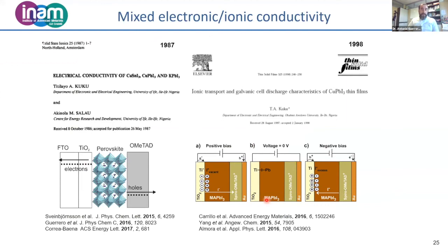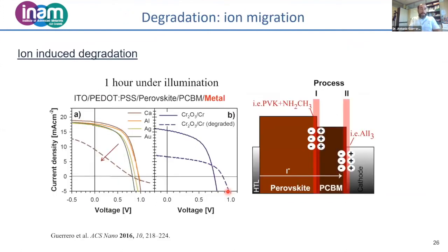Well, perovskite solar cells, as you know, are mixed electronic and ionic conductors. This has been known for a long time, from 1987 and 1998. There are some papers on the mixed electronic and ionic conductivity of perovskites. And then once we had the perovskites, MAPI and all this family for solar cells, this has been proved as well later on. Also, the ions have very important effects on the operation mechanism of the cells. They totally change the operation of the JV curve by introducing injection barriers, and also by leading to chemical reactions at the contacts.